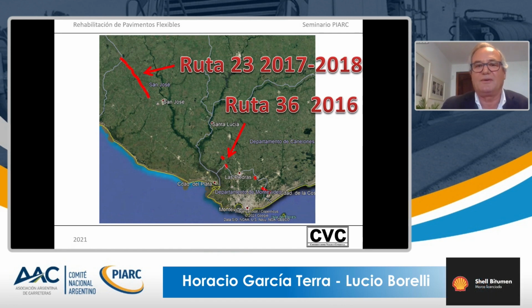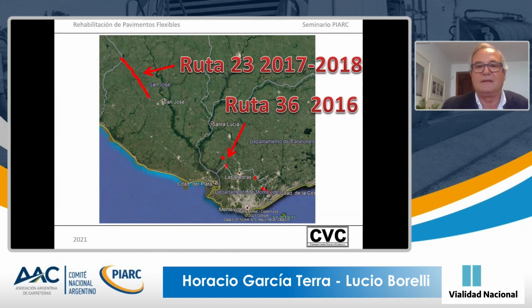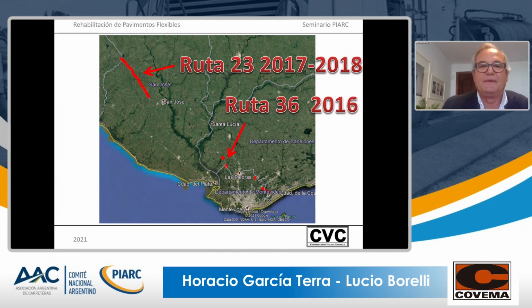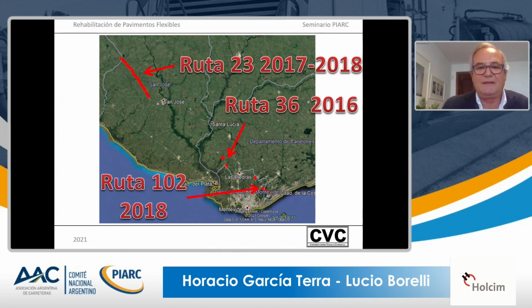We need to mention here that all these interventions were done following the South African technology, the one that is in the guideline for bituminous binder for foam asphalt. The stretch in Route 23 was 30 kilometers long, and we recycled the materials from the existing pavement, and the only new addition was the 4 centimeters overlay wearing surface.